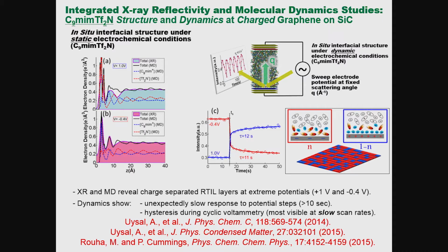But the MD simulations give us the ability to predict the distributions of the individual ions at the interface. We get a pretty good match on the total electron density calculated from MD. Some discrepancies a few layers away from the surface, but the major interactions are captured.